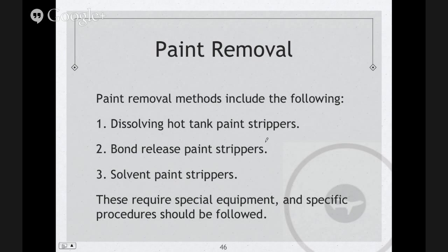Now they come and they sand it, and now you have no more paint, and you ask the person, how did you remove that paint? And they say, oh, well, we grit blasted, or we sandblasted, or we sanded, or we power sanded. Then you automatically know that if you were to do the test, maybe you may not get indications, but maybe that's because you have smeared metal, and you're not going to get it.